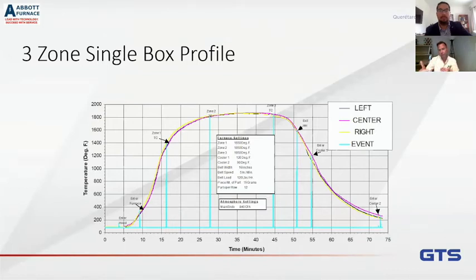It may eventually reach the high temperature. For instance, you notice here we peak out at about 1850 degrees, right where our zone 3 is. But prior to that, as we're heating up, we aren't even close to the actual zone temperatures. Right. Most of our customers ask us, well, why am I having troubles with brazing since my set point is really, really high, so I should get that temperature. Well, that's what the thermocouple of your furnace says, but that's not the whole furnace. That's correct. Just because the thermocouple of the furnace says you are very high temperature, that doesn't mean you gave it enough time to get there. Correct. Right. So that's why that profile is so important.